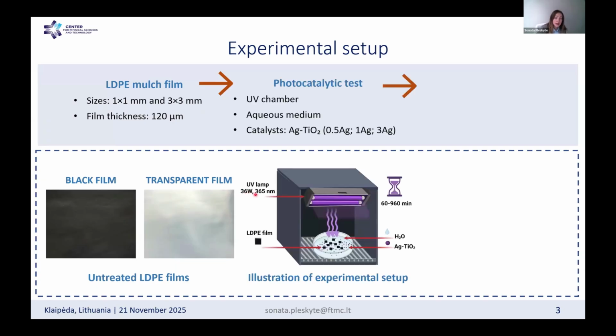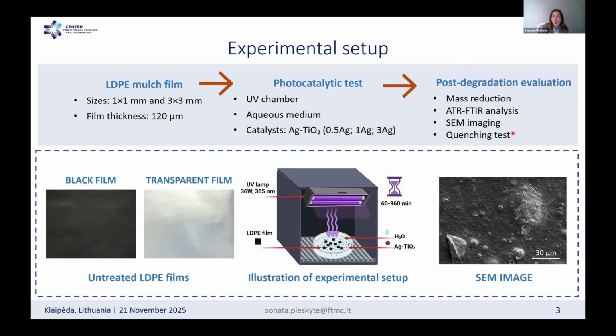So to move further, we synthesized silver titanium dioxide nanomaterials by the photoreduction method, and these nanomaterials contained different concentrations of silver, and we used them as a catalyst in our degradation system. Also, I want to mention that the presence of a crystalline phase of titanium dioxide and the successful deposition of silver on titanium dioxide was confirmed by different analytical tools, and the average size of silver nanoparticles was approximately 20 nanometers. The photocatalytic degradation performance and efficiency were determined by mass reduction and FTIR spectral analysis, followed by SEM imaging. In addition, we also performed a quenching test to determine which reactive oxygen species were most involved in the titanium dioxide-driven photocatalytic degradation system.